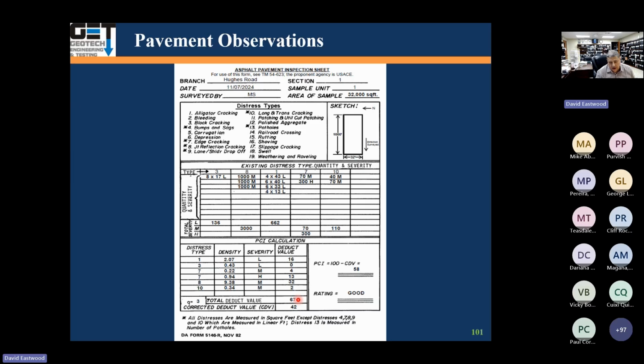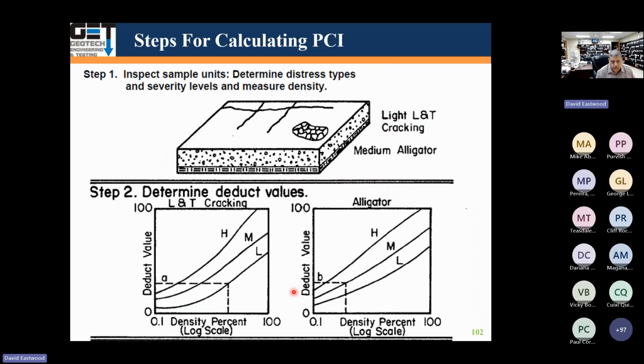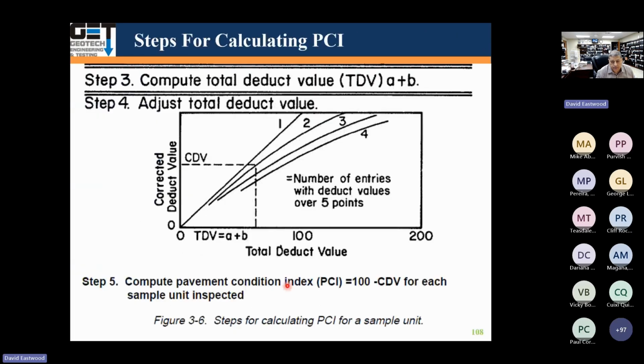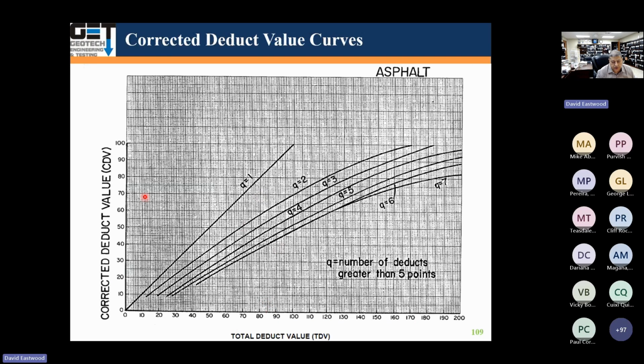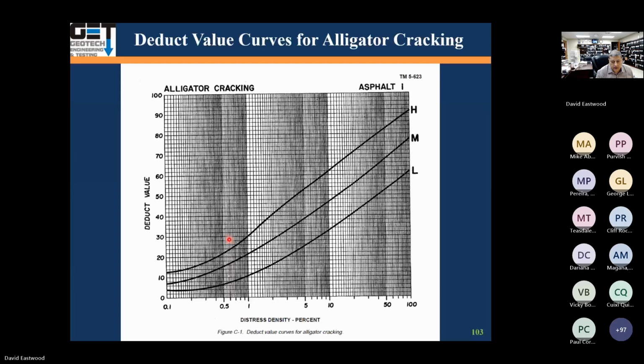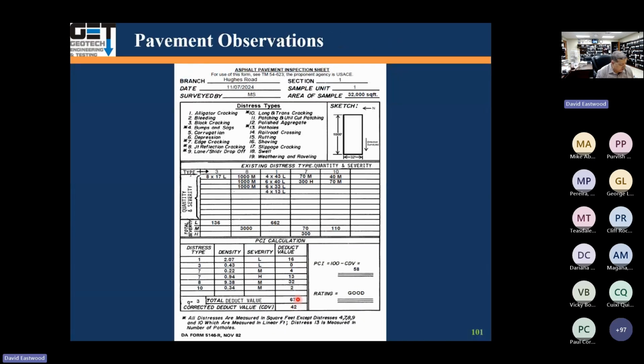And so after you get that, there's what's called a corrected deduct value, CDV. Okay, so you got to make a correction on these things. And the way you do it is, after you go through these charts, you look at total deduct value, and here's the number of the entries with deduct values of over 5 points. And then here you get the corrected deduct value. Okay, this is the actual chart in here. So if you go back again, our total deduct value was 67. And the things that were higher than 5 was 1, 2, 3. 3 of the deduct values were greater than 5. So you got only 3 of them. 67 and 3 values greater than 5.